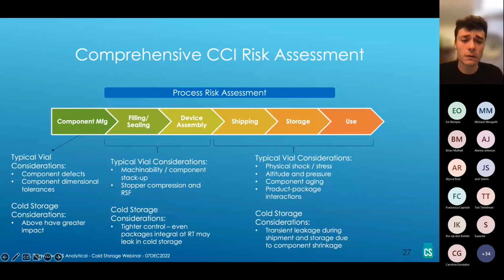During filling and sealing, typical considerations for vials, of course, include the machinability and component stackup, how we go about crimping those vials based on the compression of that stopper and its residual seal force. For cold storage applications, we need even tighter control in this area because even packages that are integral at room temperature may leak once they're placed into cold storage. And so there's extra scrutiny placed on these attributes, this process and these package components for cold storage applications specifically.